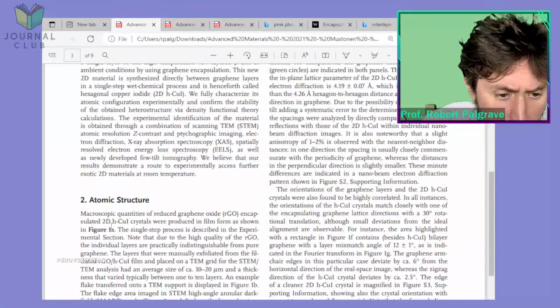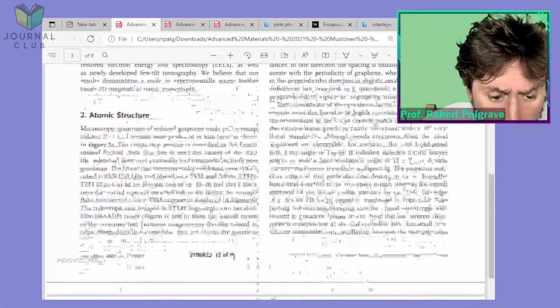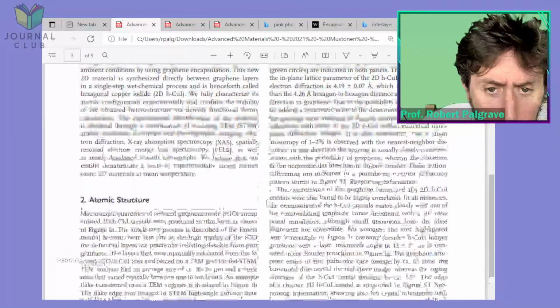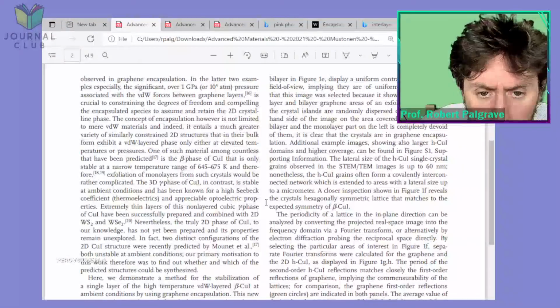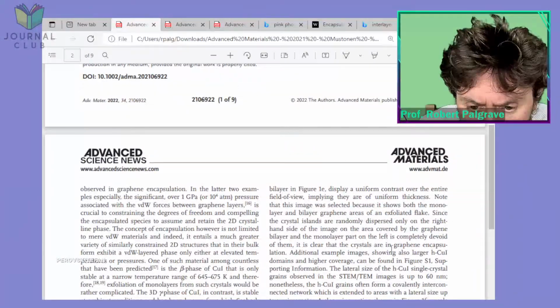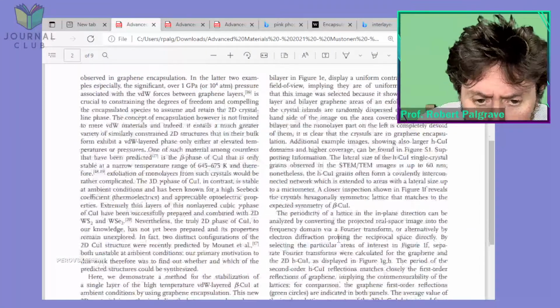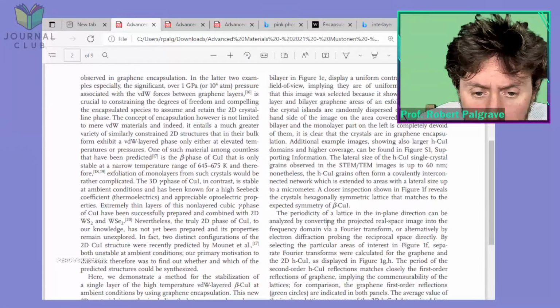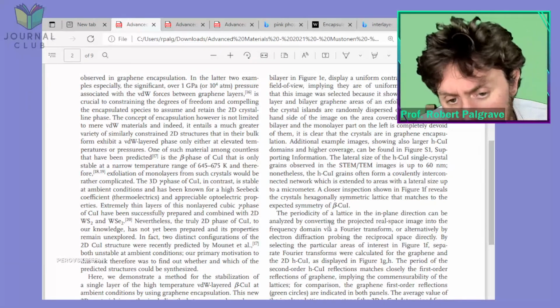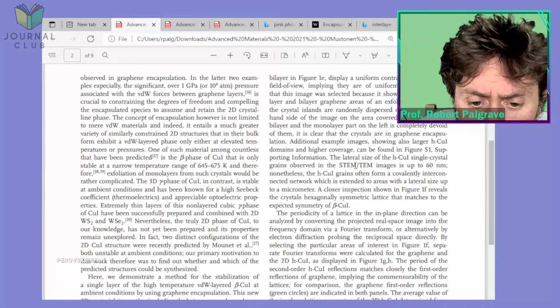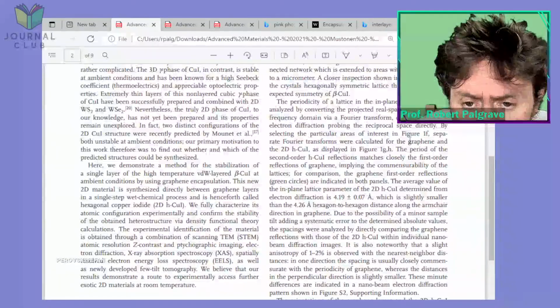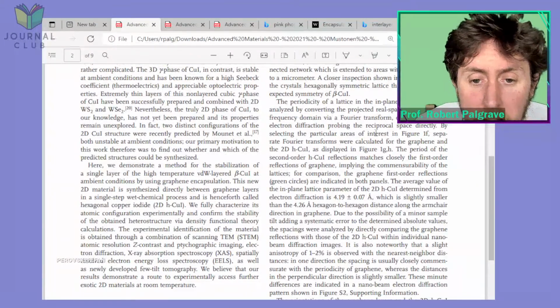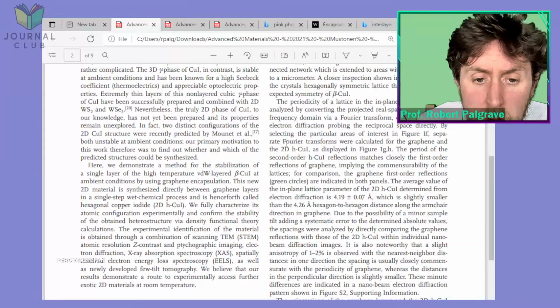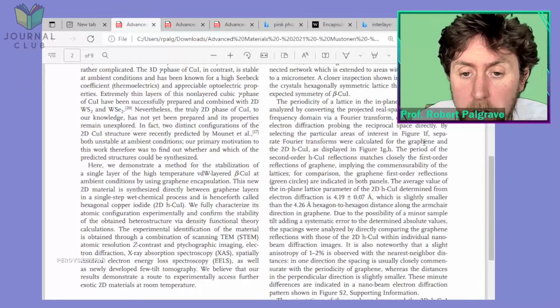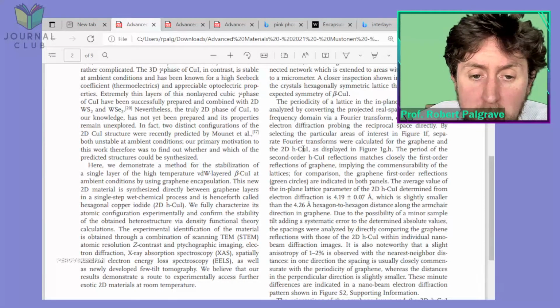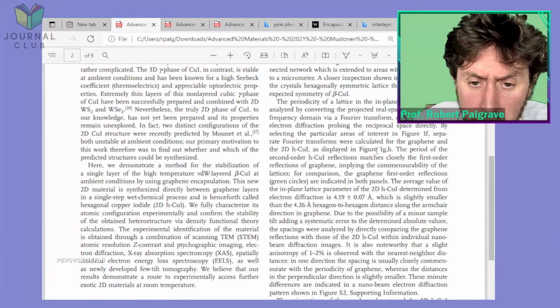Macroscopic quantities, and so on, shown in Figure 1a. Okay, I really want to see what they say about Figure 1f. The periodicity of the lattice in plane direction analyzed converting. Do they have anything about 1f before this? Okay, by selecting particular areas of interest in Figure 1f, separate Fourier transforms were calculated for the graphene and a 2D hexagonal cuprous iodide, as displayed in Figure 1g,h.